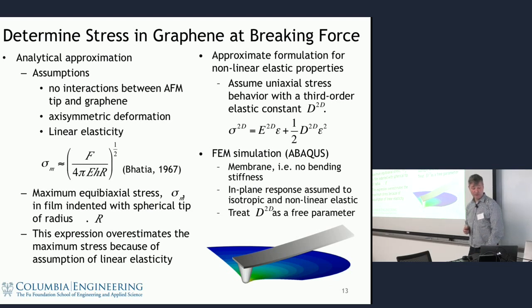So what we did in this first paper is do the simplest model of nonlinear stress strain behavior. Here's Hooke's law, F equals kx, and we just added one more term, a quadratic term. We had no idea what this quadratic term was, but this will be negative, so it gives us an inverted parabola. And if we assume that we're breaking at the intrinsic strength, that means we're breaking at the top of the parabola. Then by changing this value, we can change the stress strain behavior and run a simulation. We repeated the simulations for different values of this parameter d.